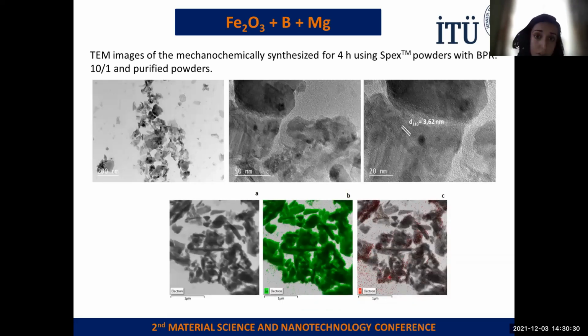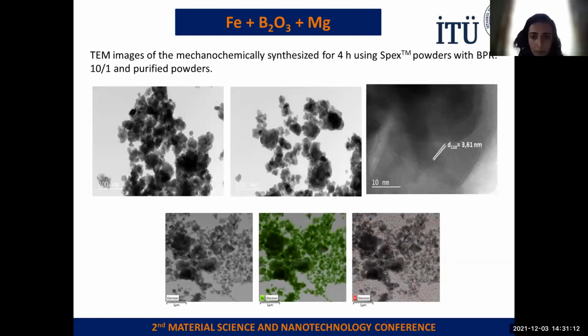Also, this transmission electron microscope image belongs to our second batch, the second raw material batch. Again, we can see the iron and boron locations, but the iron is really intensely distributed in the structure. The boron is detected at just a few points, but this spacing again shows us the diiron boride synthesis. And this is the last one, and again we can see the iron boride synthesized, and we can see the irregular shaped nanoparticles based on the transmission electron microscope image.